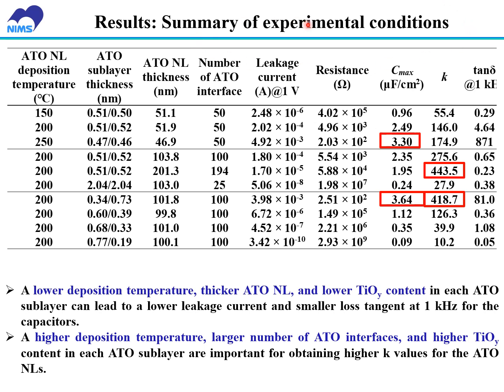This is a summary of the experimental conditions' effect on the electrical properties of the MIM capacitors. The maximum capacitance is as large as 3.64 microfarad per square centimeter, and the K value is as large as 443.5. We can conclude that a lower deposition temperature, thicker ATO nanolaminate, and lower titanium oxide content in each ATO sublayer can lead to a lower leakage current and smaller loss tangent at 1 kHz for the capacitors. In contrast, a higher deposition temperature, larger number of ATO interfaces, and higher titanium oxide content in each ATO sublayer are important for obtaining a higher K value for the ATO nanolaminates.